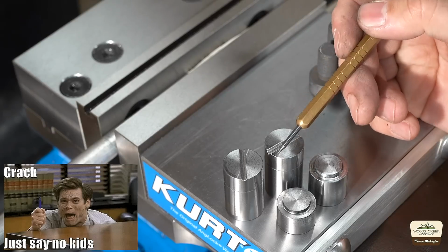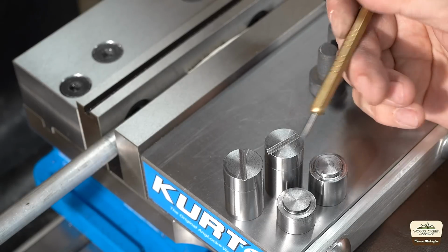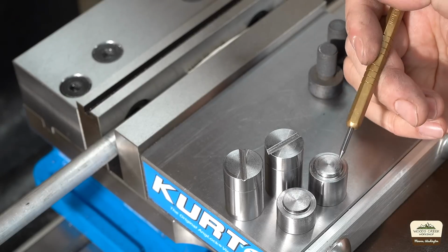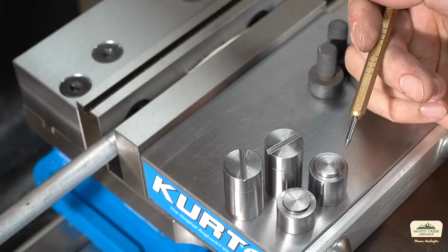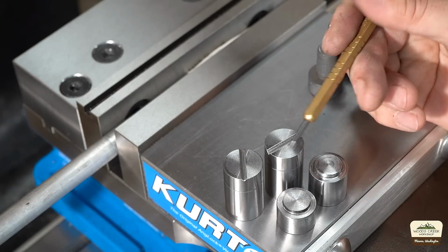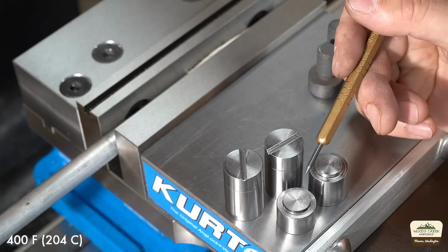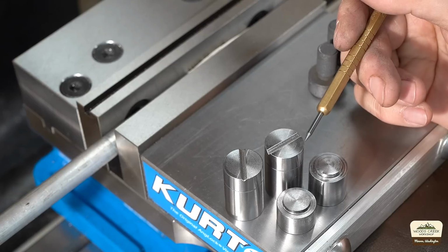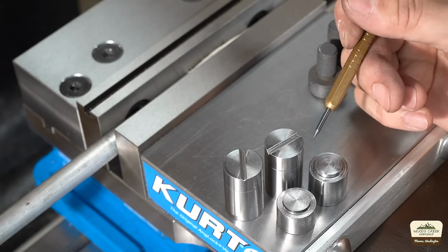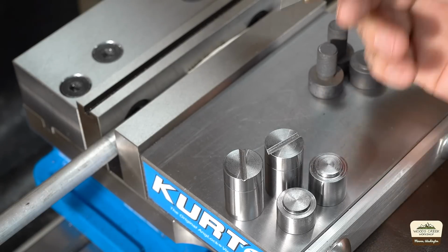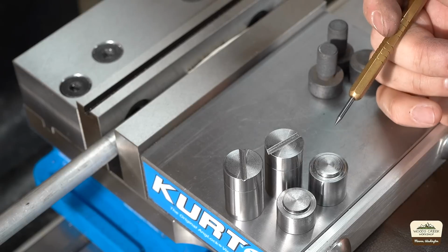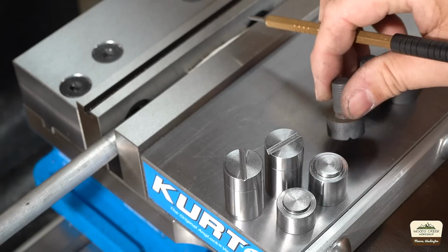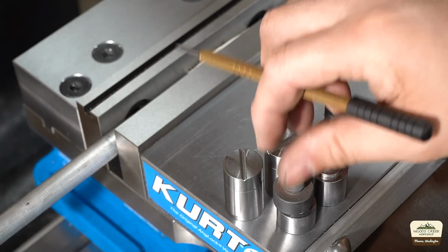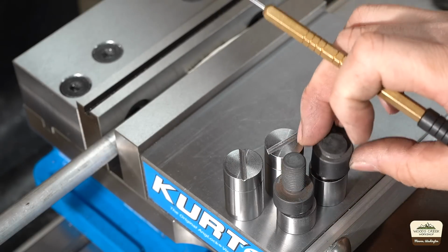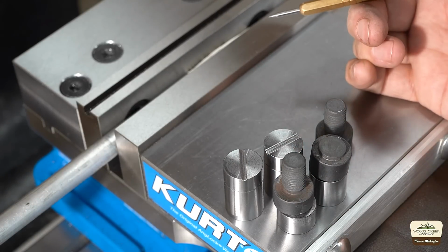Now, you do sacrifice some hardness when you prolong the quenching process, but these are pretty hard still. I did temper at 400 degrees for 2 hours. It should be around Rockwell C50, so still where I want it for my application. But I thought those cracks were pretty interesting, so I thought I'd share with you so you know what happened.